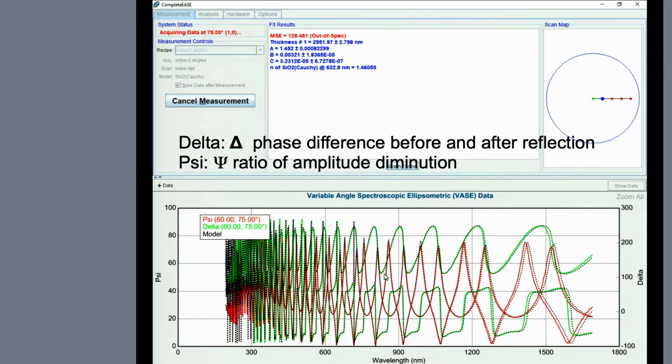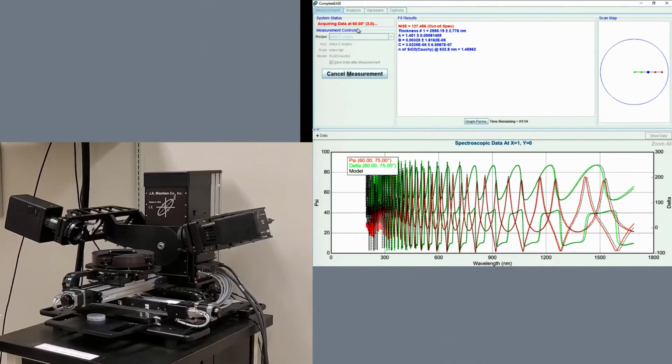A model is then built based on what is known about the sample in order to determine thickness, index of refraction, N, and extinction coefficient, K. The measured data, psi and delta, is then compared to a set of unknown properties within the model, such as thickness and index of refraction. Fit regressions are done, varying the unknown properties within the model until the measured values match the calculated values as